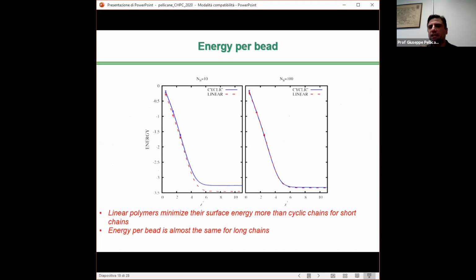Here we show the total energy per bead of the two polymer species as a function of the distance from the interface. The total energy per bead is clearly higher for cyclic polymers across the whole range of distances from the interface. In the case of short chains, look at the panel on the left. Since cyclic polymers are much less flexible than linear polymers at small degrees of polymerization, they pack less efficiently and achieve a less than optimal number of pair interactions among their beads. This aspect shows the severe constraint imposed on the flexibility of cyclic polymers by the loop topology when their chain length is small. In other words, we may say that the lack of flexibility of cyclic polymers, as determined by the loop topology when the chain length is small, is a tight constraint, and it affects their tendency to move towards the surface.